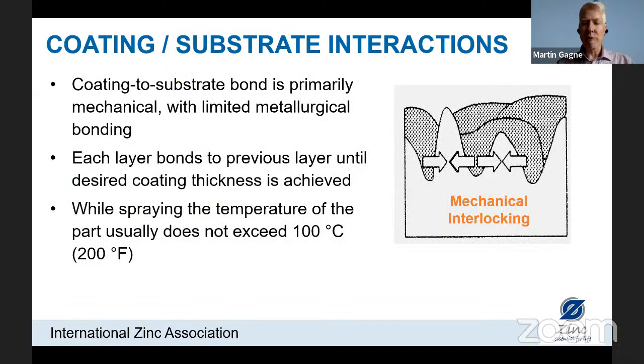Now, because we are spraying onto the steel, there is no metallurgical bond. We are talking about a mechanical bond. And this is why the surface preparation for thermal spray metallizing is very important. You have to have a very rough surface to allow that mechanical interlocking of the zinc particles with the surface on that first few layers to give us a very good bond with the steel.